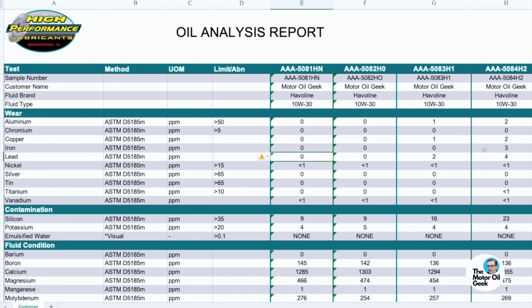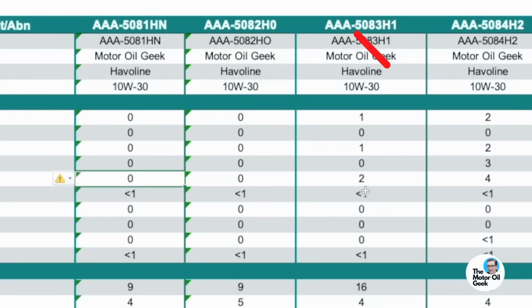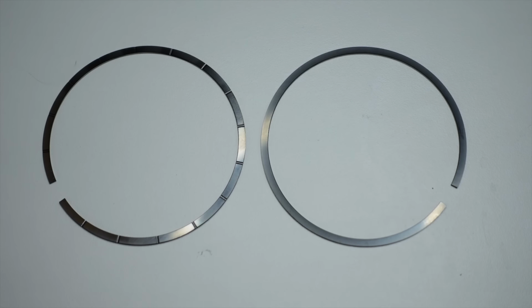And we can see that as the engine ran, as time went on, there was an increase in wear. Now what's super interesting here is that the total wear is much less than we've seen before, even with similar oils. At first I was like, wait, did they miscalibrate the ICP? Hey, run this up again. But then I remembered, hey, dummy, we were testing these new rings with the new honing process that goes along with this new advanced variable hardness coating.